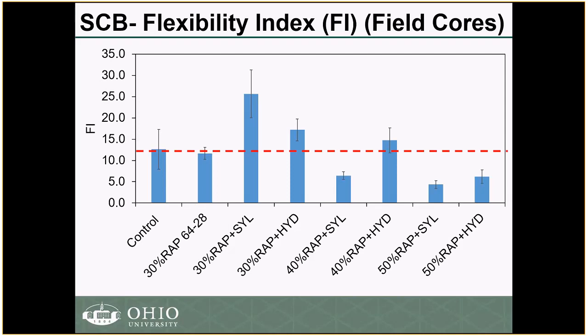This is the flexibility index. Very important, those are core samples, so they are short-term aged, if you want to compare. What you can see here is that, in general, for 30% RAP, all mixes perform well, whether it is the softer binder or the recycling agent. But when we went to 40%, the Hydroline had similar results to the control, but the Sylvaroad did not really show the same improvement that we have seen with the Hydroline.